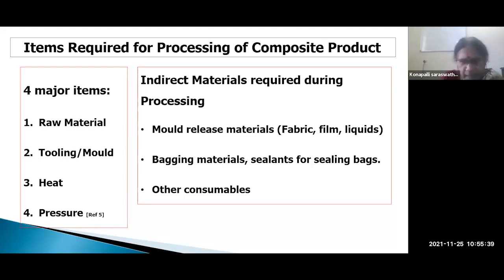And bagging materials, sealants and sealing bags we use, because as I told you, heat and pressure is applied, sometimes vacuum, because a lot of volatiles will be generated during polymerization of the polymer composites. So for extracting the volatiles and again applying pressure, we want vacuum bagging materials, vacuum bags. Those bags have to be sealed properly. So a lot of sealants are required, and many other consumables are also required.